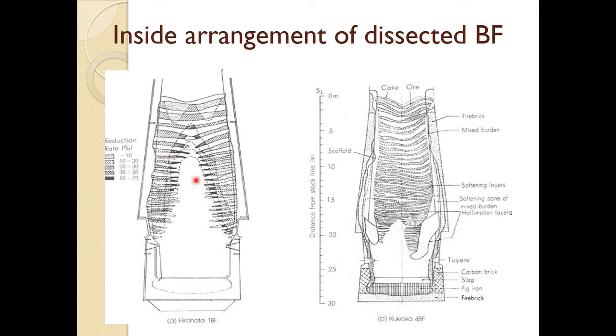Most gases pass through the coke layers because they cannot penetrate the semi-molten ore zone due to very high resistance — a permeability issue. The structure of the cohesive zone is therefore very important as it determines how gases flow into the reducing zone and affects permeability of the bed and further reduction in the upper zone.